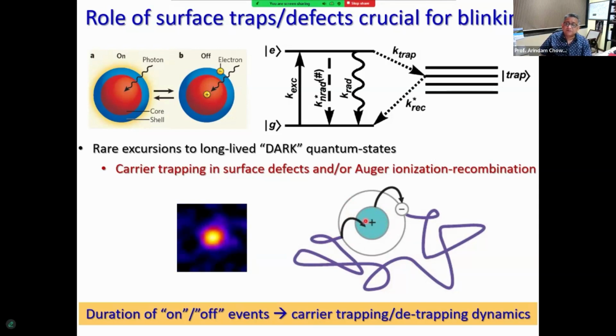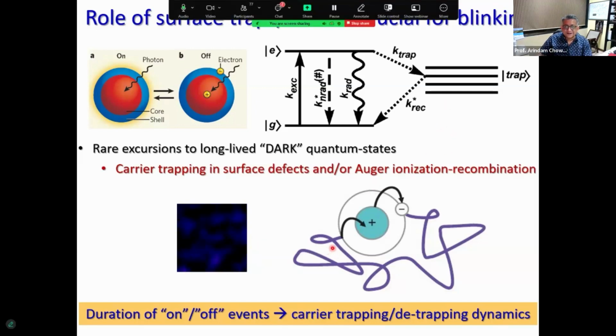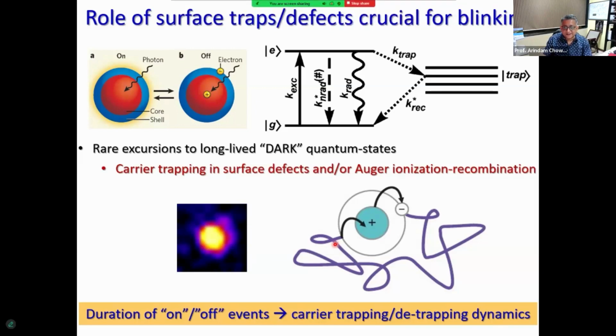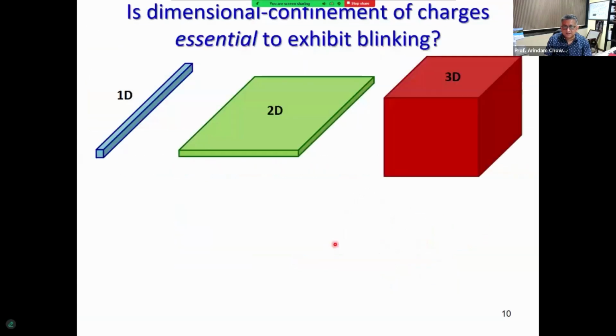And this is just one example. There are many mechanisms. This is just one of the mechanisms that have been proposed in the literature of how blinking happens. The whole idea why blinking is a single molecular or single nanocrystal phenomenon is that different molecules, as you saw in the previous slide, and different nanocrystals, they do this transition to these trap states, these sudden or rare excursions, at different points of time. And that's really the reason why this is not an ensemble phenomenon. This will always be observed at the single particle level.